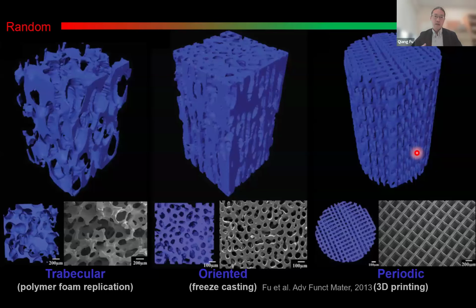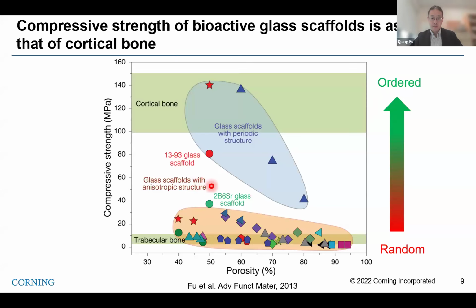Based on these ideas, we developed 3 types of glass scaffold, using the 13-93 bioglass developed by Professor Larry Hench. We used his composition, and we were able to produce these trabecular or oriented scaffolds made by freeze casting, and these periodic scaffolds made by 3D printing. This shows micro CT images and also SEM images, just to give you some idea of what types of scaffold we can make out of one simple glass composition. As you can imagine, the microstructure will definitely have an impact on the strength. When we change from a random to an ordered microstructure, we have found that the strength of the scaffold increases.